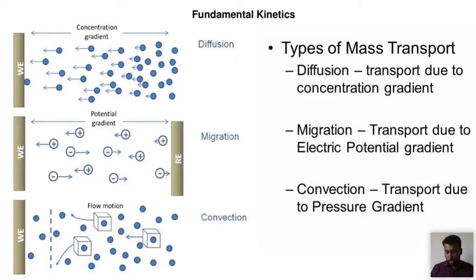In your bulk electrolyte, you will have a much higher concentration, whereas near your electrode interface, the concentration of the reacting species will be much lower. So there will be a concentration gradient between your bulk solution and the electrode-electrolyte interface. For instance, the reactant molecules from the bulk solution tend to move toward the electrode surface, from higher concentration to lower concentration. As a result, a concentration gradient will be set up. So the transport of reactant molecules governed by concentration gradient is called diffusion,